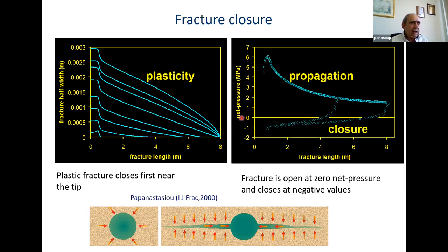In the diagram here, I have the net pressure during propagation, which was like that, and then I allowed the fracture to close after it had reached 5 meters, like that. And I propagated the fracture and allowed it to close after it had reached 8 meters. Again, you see a great pressure drop when we stop pumping without changing the fracture length. And then the pressure drops and the fracture closes completely at negative net pressures. So if we interpret the closure stress from this point, we will underestimate the net pressure.